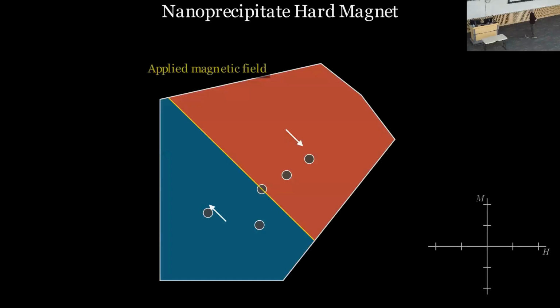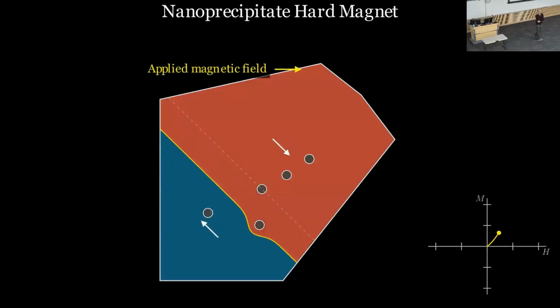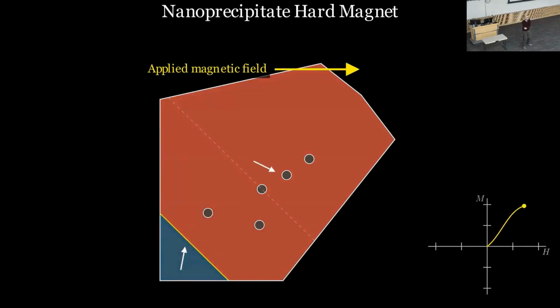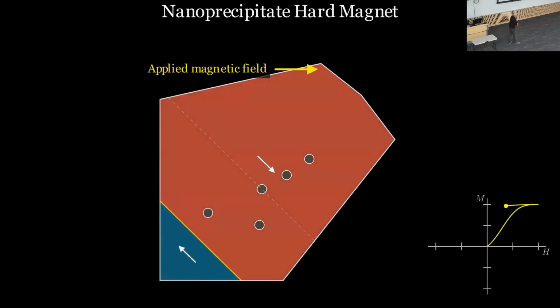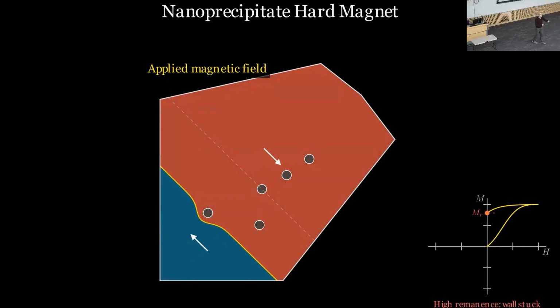Here's another model. This time, it's basically the same. All I've done is put in some defects, little spheres. And what those basically act as is a kind of friction to the motion of the yellow wall as it moves through. And what's really advantageous about that is that when the sample is trying to demagnetize itself, it can get stuck on those defects.